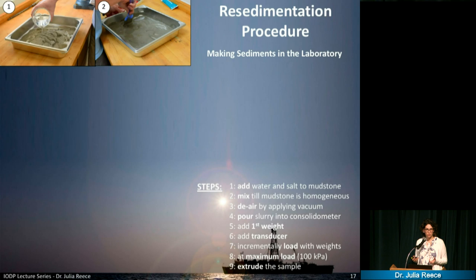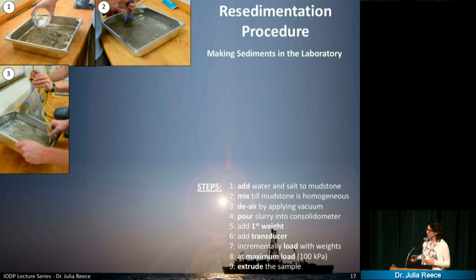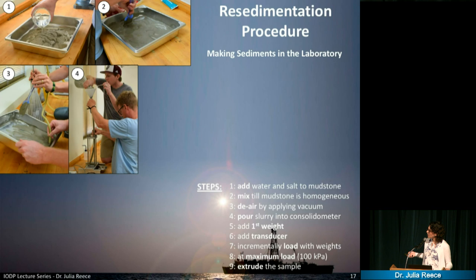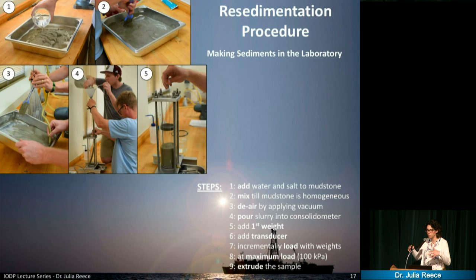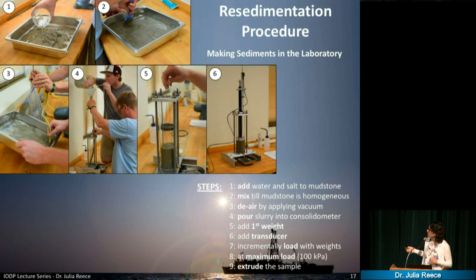And then we de-air the slurry. That means we are pulling out air bubbles that might have been incorporated by the mixing process. And then we pour the slurry into this consolidometer. And over time, we slowly add weights on top of the slurry so that we can press out the fluids. You see different stages here. We are adding a transducer, so we can actually collect digital data of how tall the sample is and how much it shrinks with time.